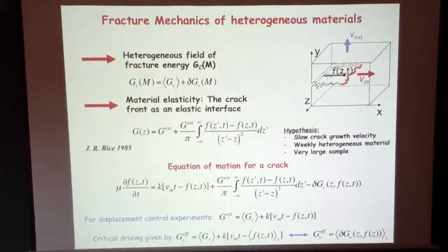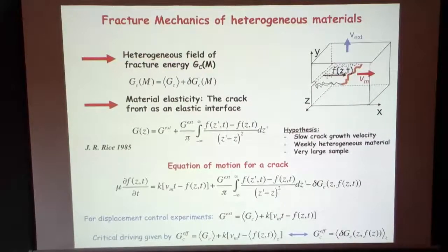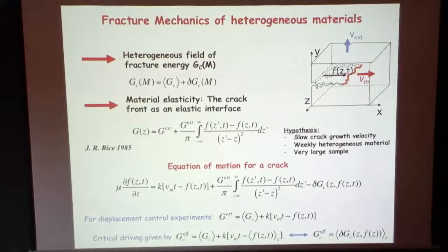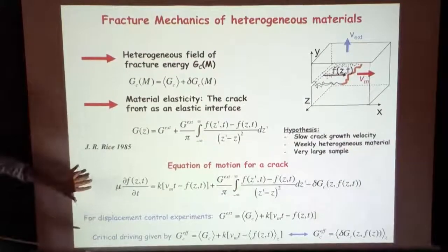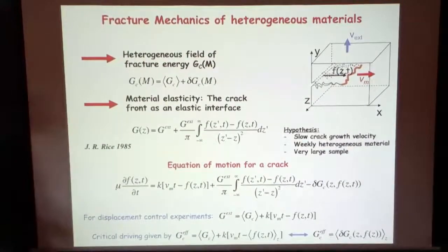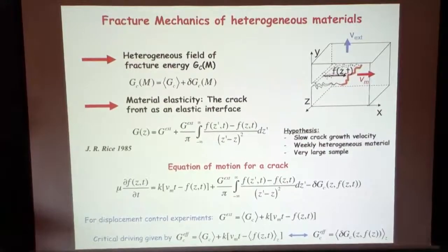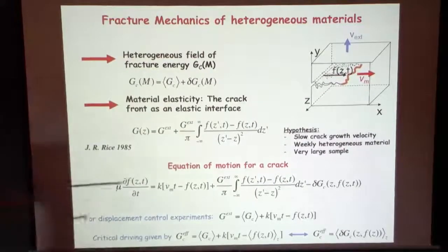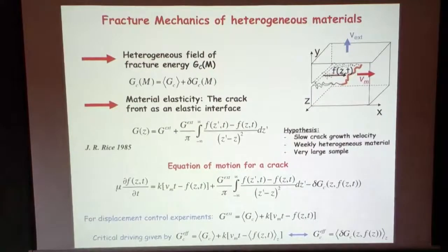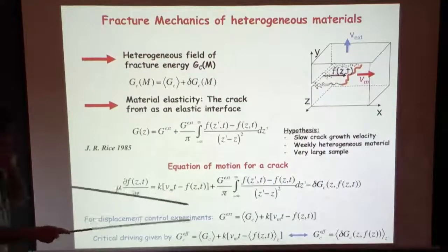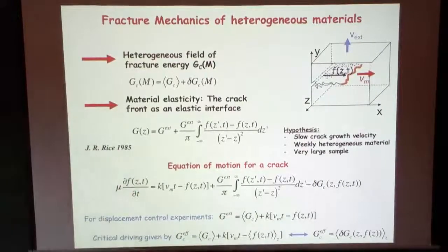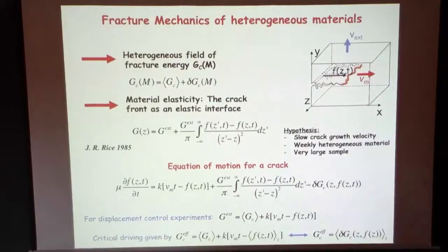So I see in your equation, mu doesn't depend on Z. Is that a really good approximation, or do you worry about that? Actually, we should ask specialists of elastodynamics. Whatever term you take, okay, we take a homogeneous term, but this value of mu doesn't change many things. So mu we take it constant, and on a large range of values it doesn't affect the result. What you finally obtain is G equals GC along the front, as much as you can. So what you're saying is the time scale doesn't really matter anyway.